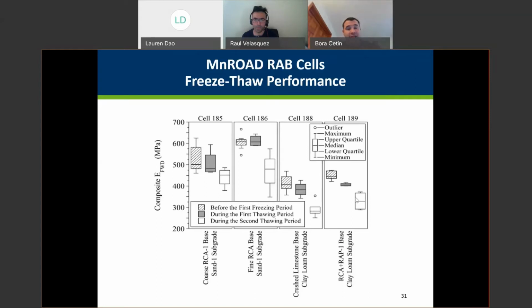One thing that I wanted to focus on here: when you look at the coarse RCA and fine RCA, after the first freeze thaw cycle, you don't see much change in the stiffness, even a little increase in the stiffness for the fine RCA. In the second thawing period, the performance starts decreasing a little bit, but that decrease rate is not as significant as what we see in the crushed limestone elastic modulus. So this graph shows that coarse RCA materials, recycled base materials, provide higher elastic modulus performance than the crushed limestone. And on top of that, they have better freezing and thawing durability for the first 2.5 years of data that we have. Next slide, please, Raul.